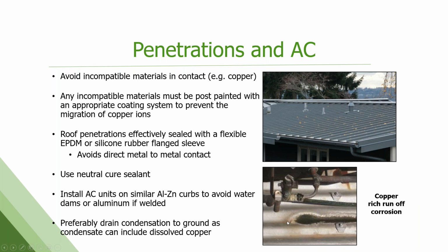Again, penetrations, avoid incompatible materials. Copper, we've got some pictures here. This is copper runoff from some piping and stuff that's corroding the panel where it drips and sits. Any incompatible material should be post-painted with an appropriate coating system to prevent the migration of copper ions. Roof penetrations need to be sealed with flexible EPDM or a silicone rubber flange sleeve to protect it from water. Use neutral cure sealants. There are technical bulletins on all the sealants that are good to use with this product and approved. Want to install AC units on similar aluminum-zinc curbs to avoid water dams, or aluminum if it's welded. And then preferably you want to drain condensation all the way to the ground, rather than it running down a roof panel.